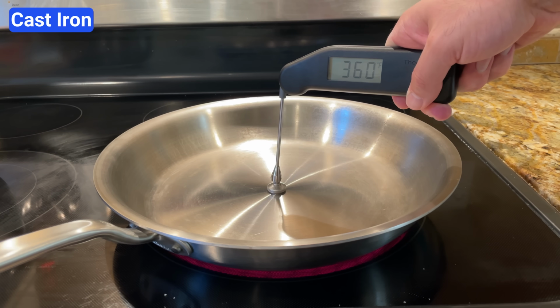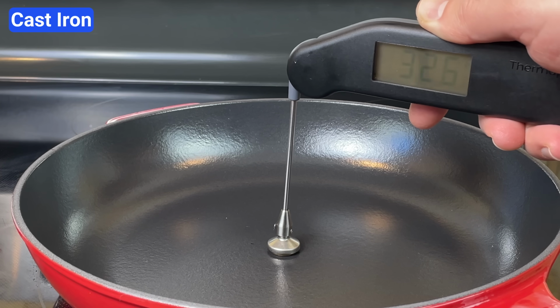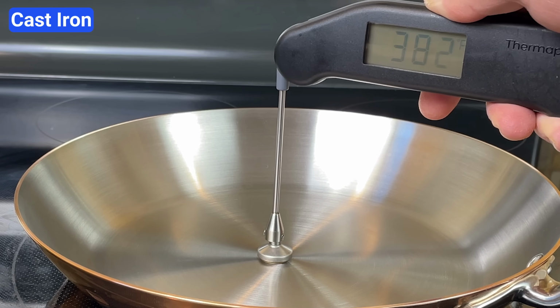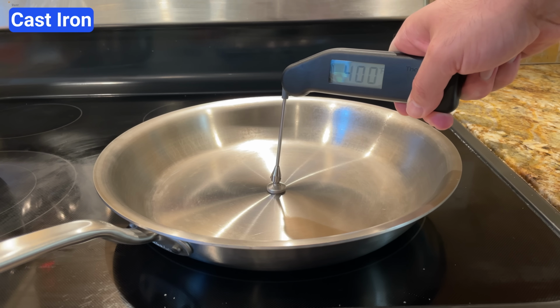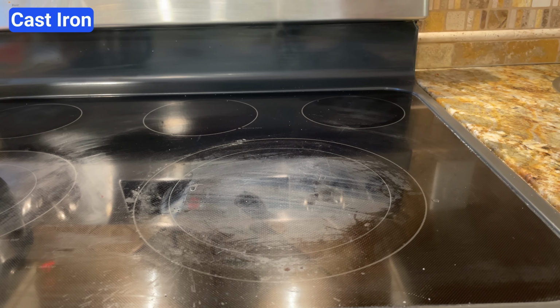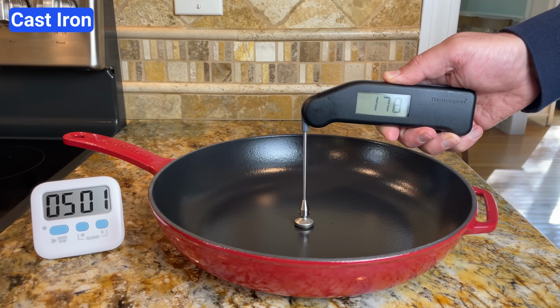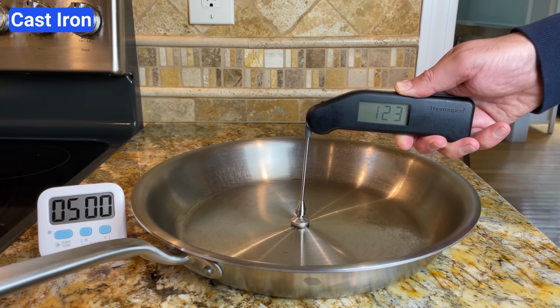To prove this point, I heated 5 pans made of different materials to exactly 400 degrees Fahrenheit. I took them off the heat and measured the surface temperature after 5 minutes. At 178 degrees Fahrenheit, the cast iron pan retained the most heat and had the highest temperature by over 50 degrees. The next closest was the stainless steel pan at 123 degrees.